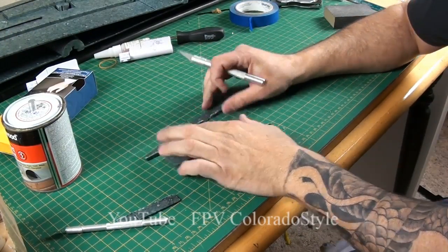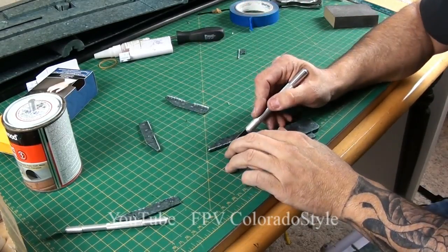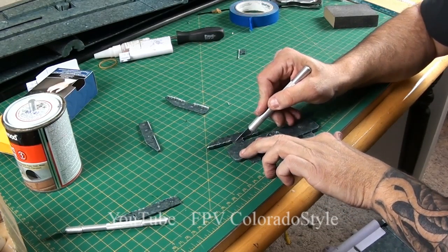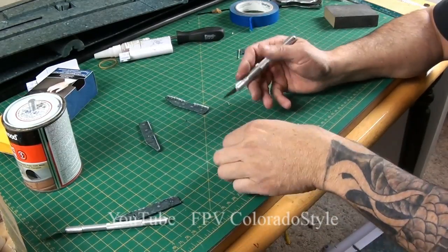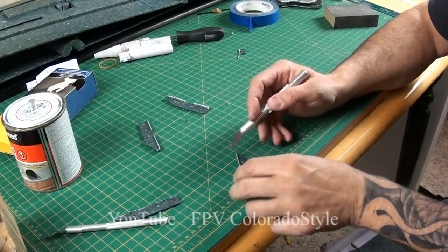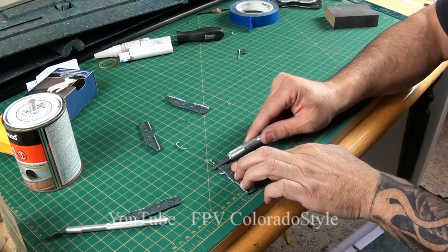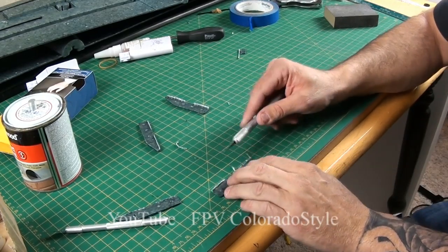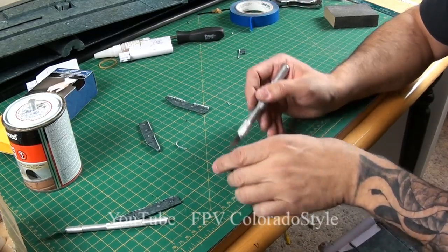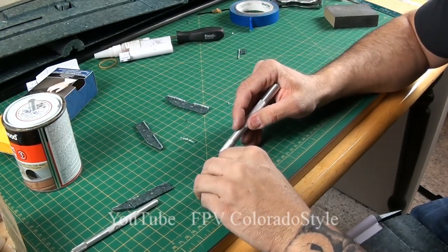I'm cutting the covers off the excess piece of foam. That excess piece of foam, by the way, is a great thing to test out different glues on. I found out that CA glue does not work — slow or fast. Contact cement was one of the few that did, and I also used 30-minute epoxy, which seemed to stick. Most glues I tried did not, with the exception of Gorilla Glue — the brown stuff did. Not much sticks to this gray EPO foam.